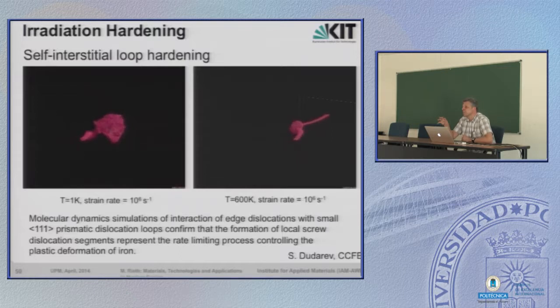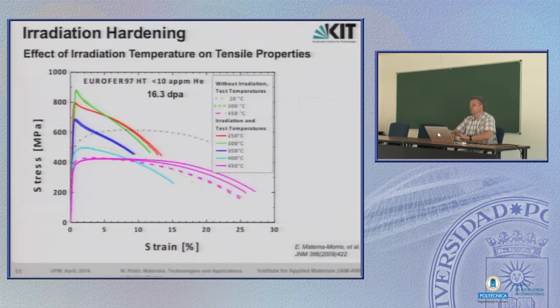At higher temperature, also due to the fact that most of these defects are recombining and going away, but also because at higher temperature dislocations can move more easily, the irradiation hardening effect should be less pronounced. This can be simulated and drawn as a conclusion from this simulation. But let's see how it works in the real world.